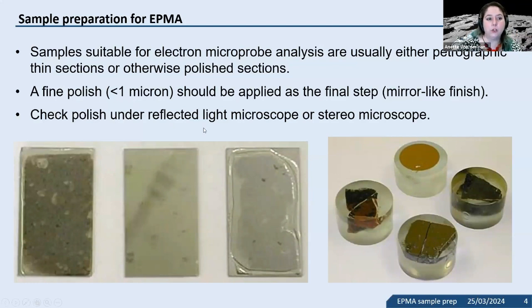What does a good polish mean? The final polish should be better than 1 micron as the final step. And this is what we usually refer to as a mirror-like finish. If you're unsure if your polish is good enough, there are 2 steps. First, if it's not shiny, it's not good enough. The surface should equally reflect back.